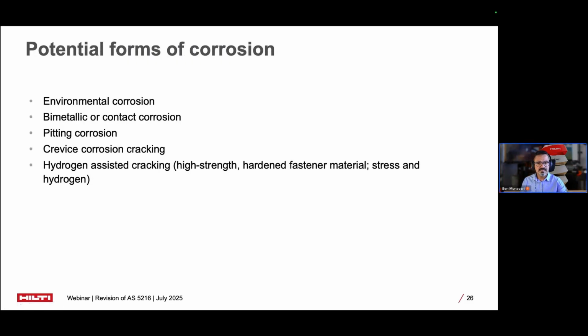The standard addresses multiple corrosion mechanisms that can affect fasteners. Environmental corrosion results from atmospheric exposure and varies significantly across Australia's diverse climatic conditions. Bimetallic or contact corrosion occurs when dissimilar metals are in electrical contact. Pitting corrosion creates localized deep penetration, particularly dangerous because it can cause failure with minimal visible indication.